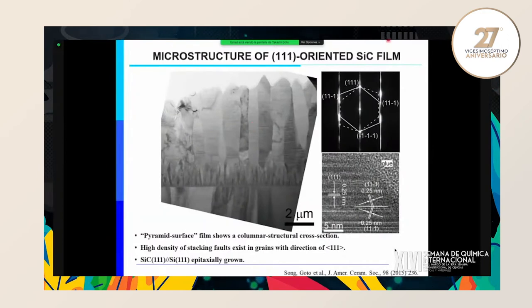So this is just a cross-section of CVD silicon carbide prepared on silicon 111. Silicon does not have so high a melting point, about 1,400. So we can make very faceted, very oriented silicon carbide, even on silicon. So all grains are oriented to the 111 direction on the silicon 111 plane. So we can obtain a thick, almost epitaxial silicon carbide film.